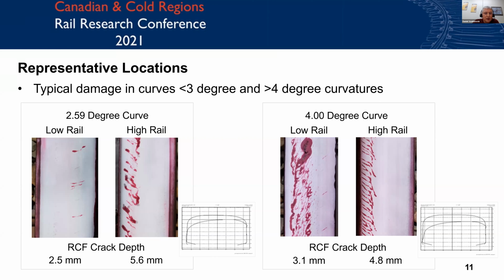There's a lot of plastic deformation and wear in that rail, and combine that with lack of grinding, since the last grind cycle here was some 15 years ago. This is the type of damage that you see in that rail. So that new rail comparison to the worn rail, you see that there's a big difference here with a lot of plastic metal flow and a lot of wear on the gauge face corner with that type of cracking.